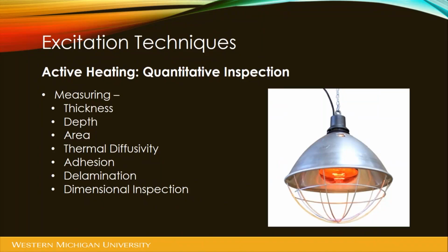We would have to do that. No, I didn't. This was kind of before thermal, but we'd have to do it. The Saab 340s I worked on used bonded metal skin. Have you all seen how bonded metal works? Basically using an epoxy, the epoxy ribs on. So they didn't use rivets to hold the skin to the formers and the stringers and the ribs. They were bonded. And it was actually 2 layers of metal that were bonded together as well. So if they got a dent in them, it could pop that apart. And particularly if that dent was in, you didn't want it to oil can and pressurize.